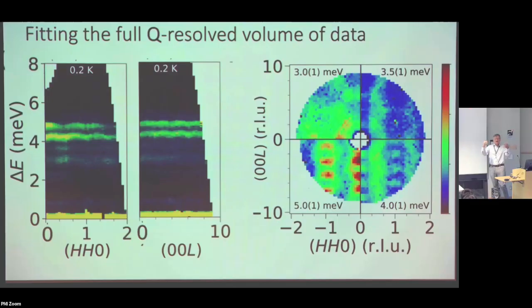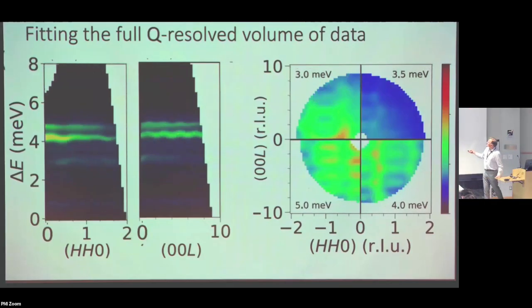And that required using a cluster computer, because there are really tens of thousands of pixels, and you have to do this fairly complicated calculation along with that. So we had never tried something like that before, and it really was only possible because of the power of the instrument and because of the computational advances. We would never have been able to do it on computational capacity from, let's say, 10 or 15 years ago. It was a pretty high level thing, and then you end up with this type of agreement. So that's the experiment. This is the RPA calculation, and many of the features are quite well reproduced.